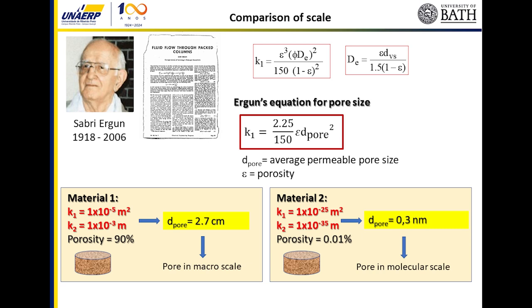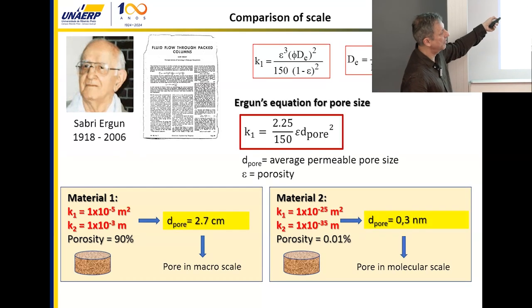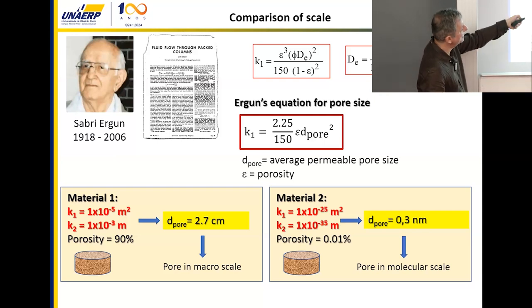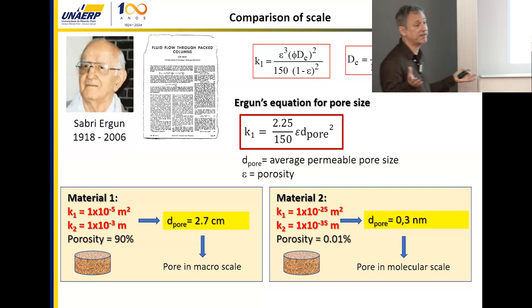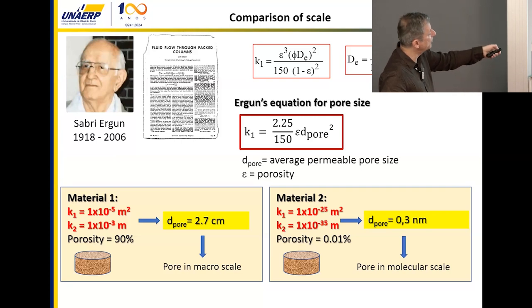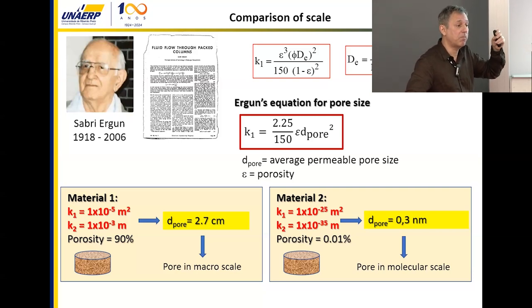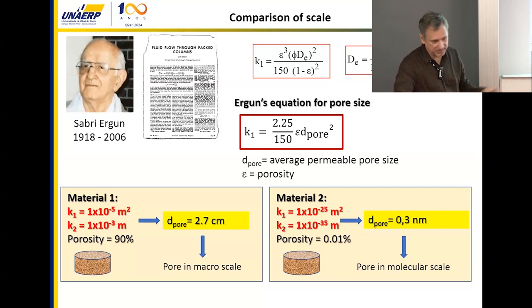This is his famous paper, where we got the relationship that I told you about the K1 with the porosity and with the equivalent diameter. And if you replace the equivalent diameter with the pore size, we can have this kind of equation. This equation I have used in the lab, and it's very interesting because if we measure, Juliana, the K1, which is easy to measure, and if you measure porosity, which is not a complex thing to measure, the total volume of pore, then we can predict a typical size of pore, which is a permeable average pore size. It's not the complete pore size, the average pore size, which is permeable to a fluid.